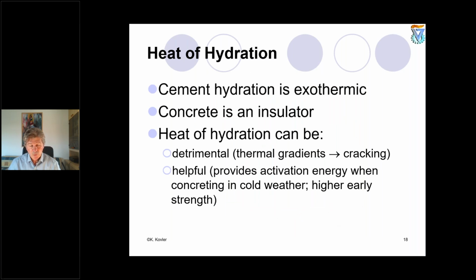When we speak about hydration, we understand well that cement hydration, like hydration of many other mineral binders, also gypsum and lime-based systems, is exothermic with liberation of heat. Concrete is an insulator, and heat of hydration can be either detrimental, for example, when we have thermal gradients, especially important for mass concrete structures, resulting in cracking, but also helpful, especially in winter time, in cold regions, which provides activation energy when concrete is in cold weather, and resulting in early strength.